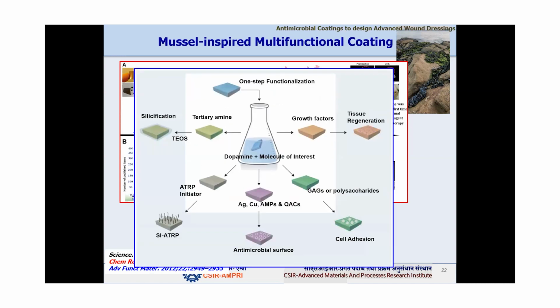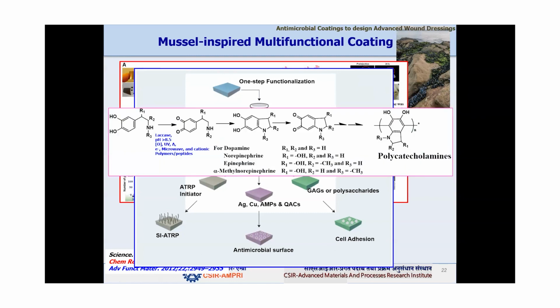Another important point is that if you want to do a polydopamine coating on any substrate, the mechanism is very simple. You just take the substrate, put it in a dopamine solution, and maintain a pH of 8.5, and your substrate will be coated. Later on, you can attach different kinds of components like tertiary amines, growth factors, metal ions, or antimicrobial peptides, for applications like tissue regeneration, antimicrobial surfaces, and cellular adhesion. The chemistry is very simple and easy to use, so there is enormous growing interest in this particular field.